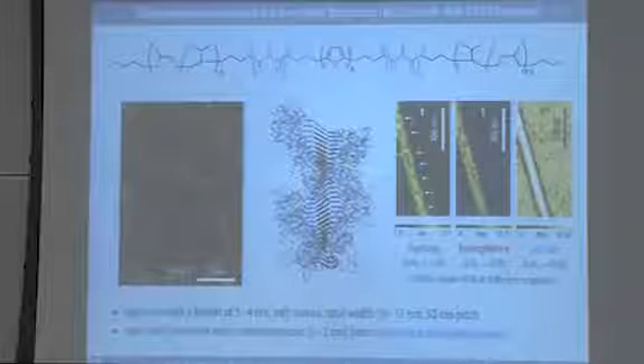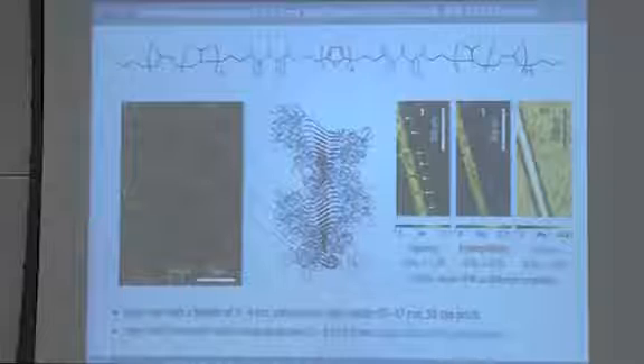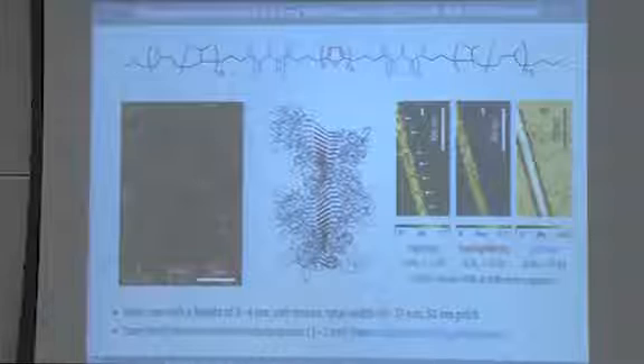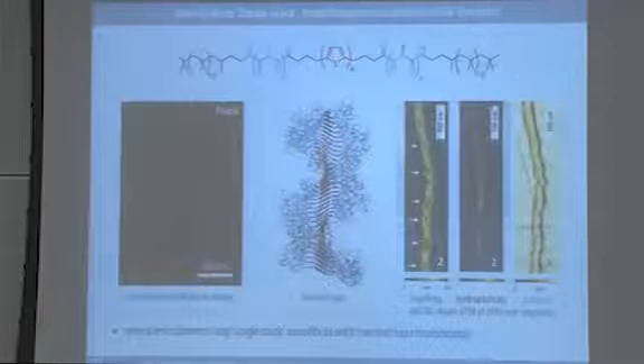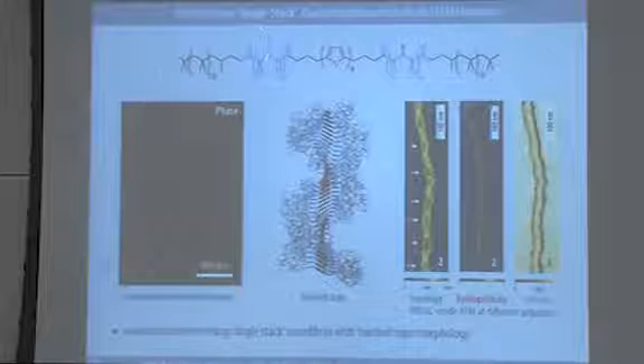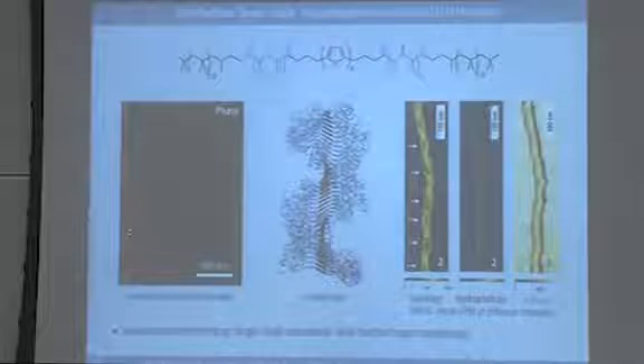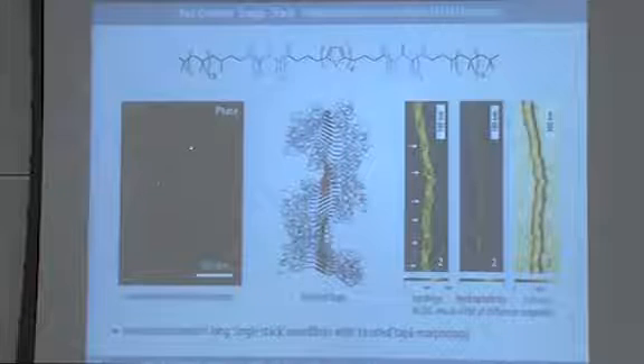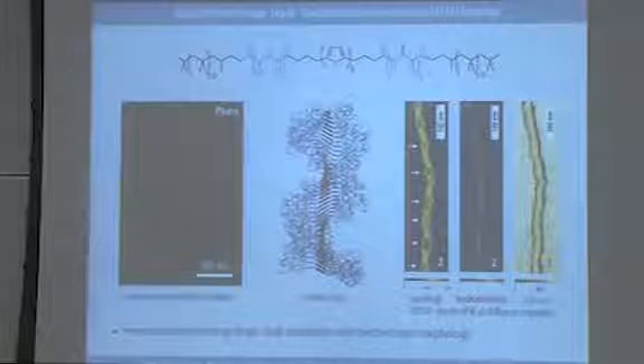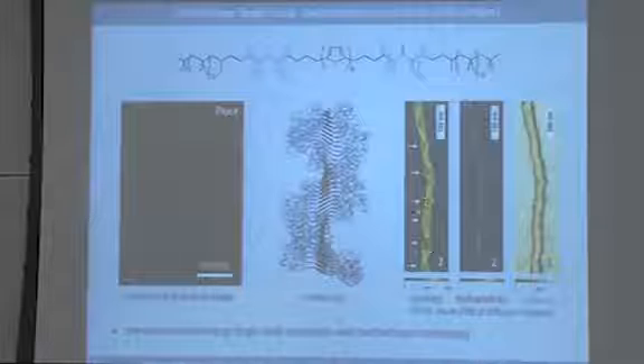And I'll show you two more such images just to give you a complete overview that this is kind of a universal scheme. So here we looked at a molecule that had a quadrithiophene, a tripeptide, and hydrogenated polyisoprene as polymer segment. We can change most of these parameters, so we can go to a tetrapeptide, we can exchange the polymer for polyisobutylene. Again, you can see very well-defined fibrils. In this case, even the conventional AFM image shows a nice helicity, the same helical morphology for all the fibrils, and the MUSIC mode shows height corrugations and again soft material placed along the edges.